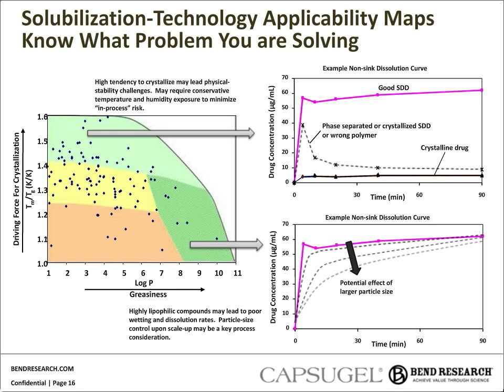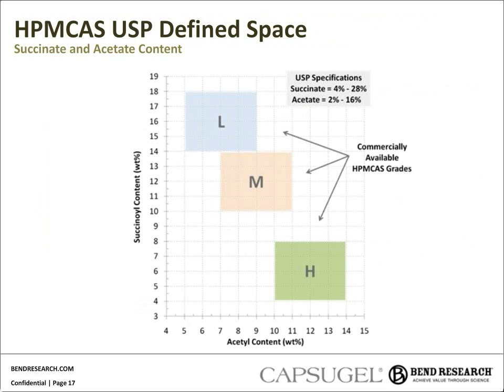In the alternate case study on the bottom, we're talking about drugs that don't have a strong propensity to crystallize, but they're very lipophilic and therefore hard to get dissolved. What we need here is a rapid dissolution rate, and particle size, as determined by the process, can strongly determine the success or failure of a dispersion in this regime.